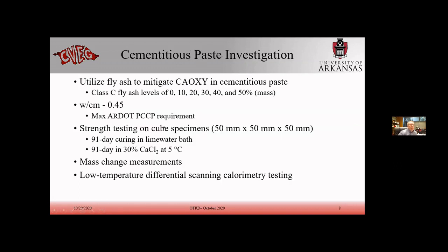So the first thing we'll look at is paste. We're just talking about paste, which is cement and water. We looked at the reduction in cementitious contents or additions of Class C fly ash of 10, 20, 30, 40, and 50%. We used a paste mixture with a water-cement ratio of 0.45. That's what the Arkansas Department of Transportation requires. That's the maximum water-cement ratio they require for their Portland cement concrete pavements.